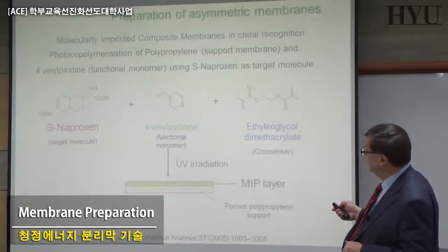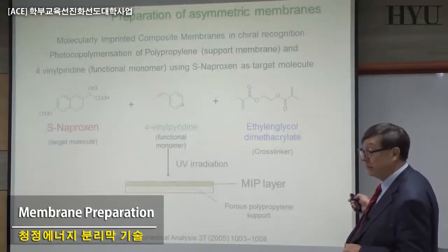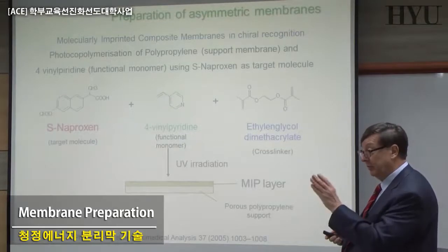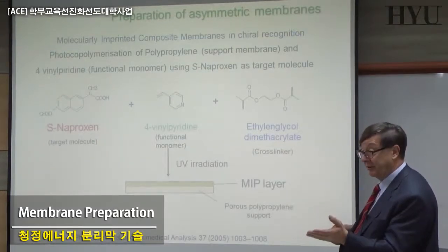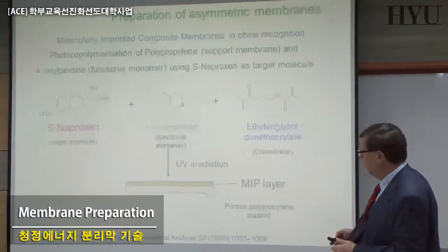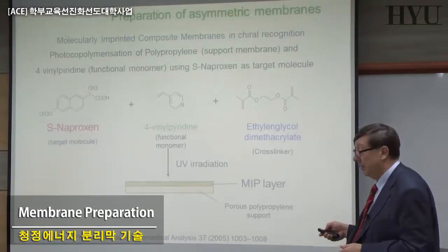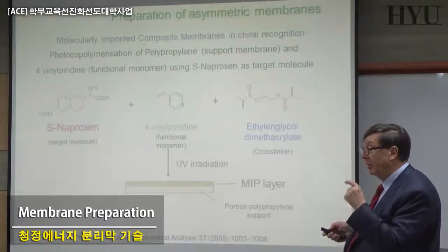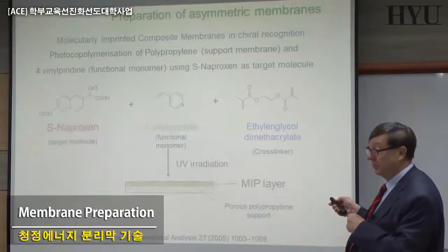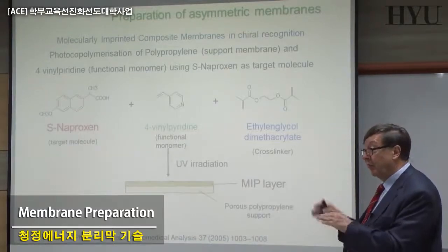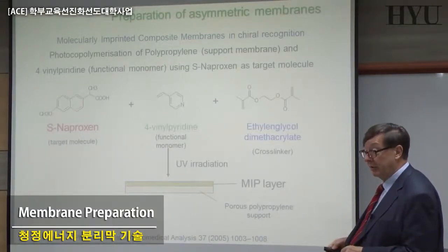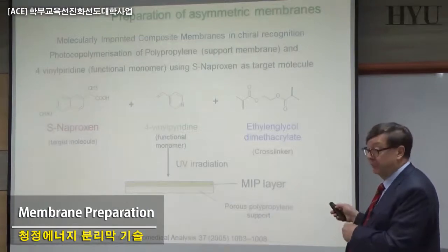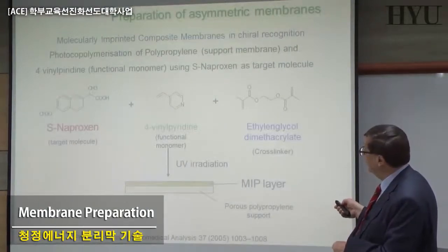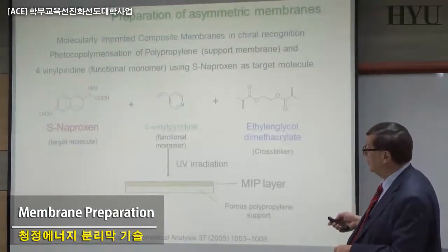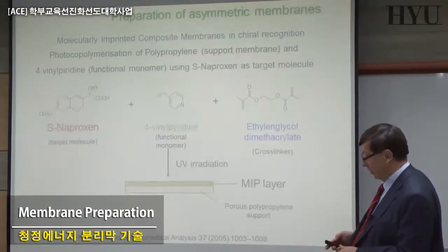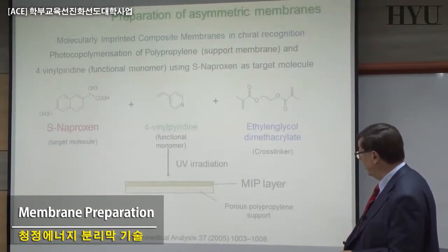And imprinted composite membranes can be utilized in chiral recognition. You can select between the left form and the right form with the system, just by producing some membranes in which you induce memory in these imprinted composite membranes for a specific selectivity. This is not selectivity of the polymer, it's selectivity related to what you are putting in, this functional monomer, basically. And that's quite interesting, and it works.